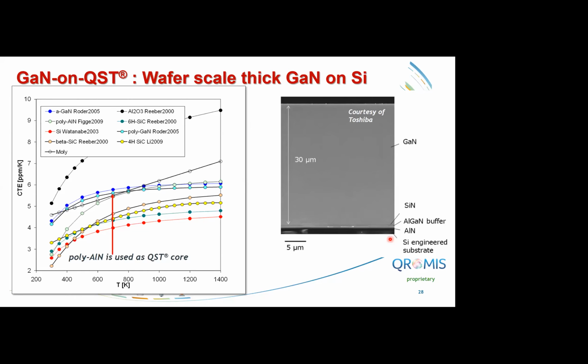How about the thermal management about thin gallium nitride or diamond? If it's pure gallium nitride, the thermal management in a vertical device is actually much easier than lateral device because you have the whole volume to dissipate the heat. And people have shown this from experimental data and simulations. But if it's on diamond, there are some exciting results, to be honest. But again, if you have two different materials, you have a thermal boundary there. So that boundary has to be dealt with smartly. So there are issues, but there are also promises there. Thank you very much. Thank you for the question.